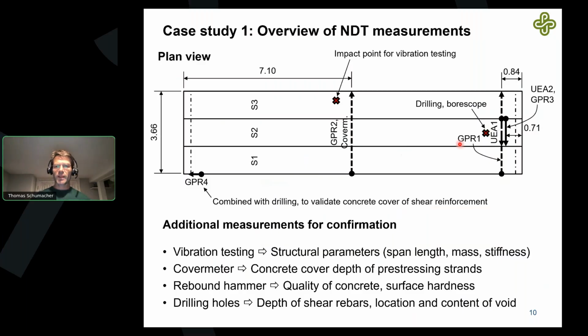I was able to convince the engineer that I wanted to drill a hole in the middle vertically from the bottom to hopefully reach that middle void that we thought should be there, so I can measure that distance, and we can also determine if there's any water inside. We then used a little camera, a borescope attached to my cell phone, to get in there and have a visual. So the images that I'm going to show you are really located a little bit closer to the support of slab number 2. I was trying to recreate a cross-section of one of these slabs in great detail.